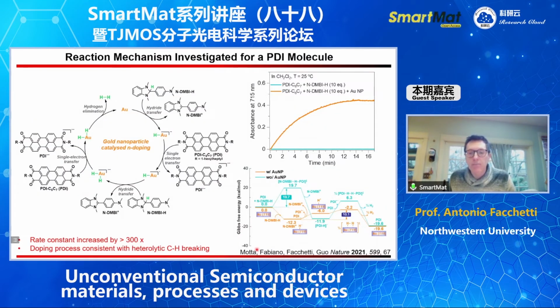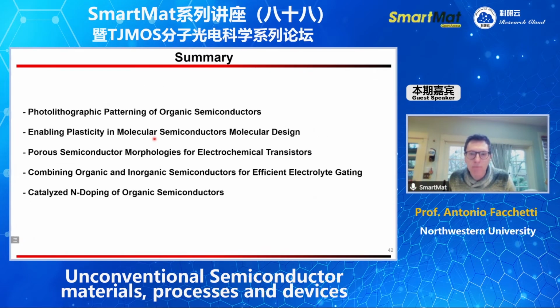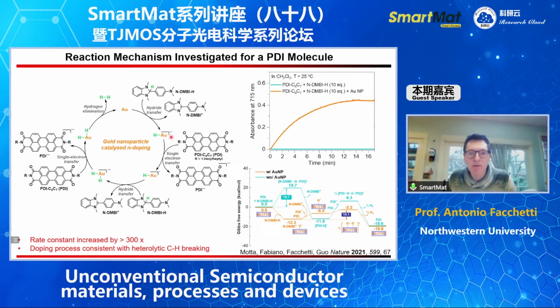We studied this reaction more deeply from the computational point of view in work with Alessandro Motta, and we studied the kinetics in collaboration with Simone Fabiano. This is the catalytic cycle, and the reaction as modeled by computation occurs by, again, breaking this bond heterolytically. So you have gold, then the hydride is transferred onto the gold, forming the negatively charged gold hydride surface. This surface can transfer one electron, so it dopes the molecule. And then this can happen another time to form the radical anion. And then it can transfer a second electron to restore the gold and then eliminate hydrogen.